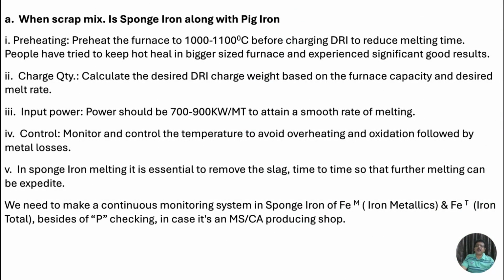When the scrap mix is sponge iron along with pig iron: Number one, preheating. Preheat the furnace to 1000 to 1100 degrees C before charging DRI to reduce melting time. People have tried to keep a hot heel in bigger size furnaces and experienced significantly good results. Number two, charge quantity. Calculate the desired DRI charge weight based on the furnace capacity and desired melt rate. Number three, input power. Power should be 700 to 900 kilowatt per metric ton to attain a smooth rate of melting. Number four, control. Monitor and control the temperature to avoid overheating and oxidation followed by metal losses.